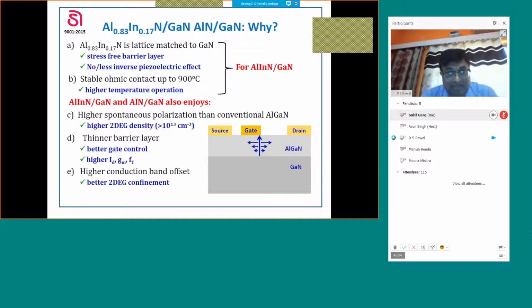And at the same time, because there is no piezoelectric polarization, there are chances that sheet carrier density may get reduced, but it is not the case, because the difference in spontaneous polarization in aluminium indium nitride and gallium nitride is very high. So that gives rise to very high sheet carrier density even with very thin aluminium indium nitride layers. That is very important for high FT or high GM devices.